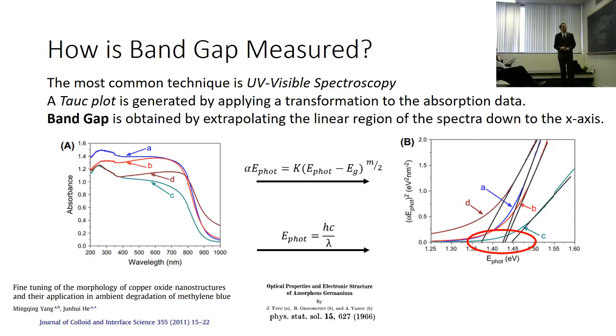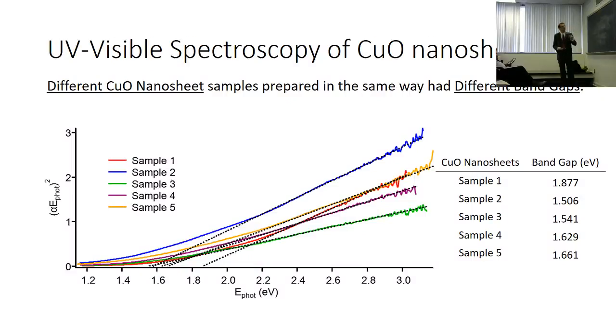Pretty simple. The third thing I wanted to do - before I get to that - so I did it on my samples. I made 5 different copper oxide nanosheets, all the same way, different batches, and I got 5 different band gaps. That's good and that's bad. It's good because everyone else was getting different band gaps too, so I was reproducing their irreproducibility, which is great. It's kind of bad because maybe I'm incompetent and just can't measure something. But then I did it a few times on each sample, and I could actually measure the same band gap for the same sample. So that was good.